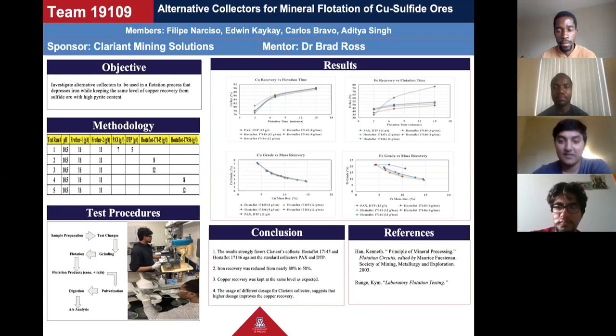Based on these two factors, the same amount of copper recovery and decreased iron recovery, we come to the conclusion that the two new collectors in use are more favorable than PAX and DTP, which were used before. So our recommendation would be to use the two new collectors instead of PAX and DTP. With that, I'd like to pass on to Felipe for the closing remarks.